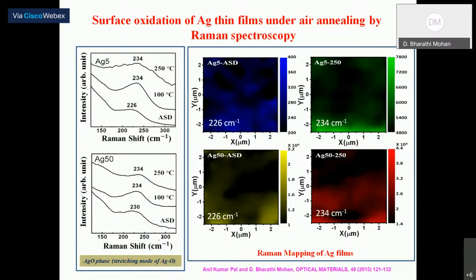One of the major problems with silver is the oxidation. So we need to study the surface oxidation of the thin film. So we have used Raman spectroscopy in order to understand the chemical structure of the silver thin film. And we found that there is a peak at 234, which corresponds to the stretching mode of silver oxide, confirming the formation of silver oxide. And the formation of silver oxide becomes much greater when you increase the film thickness and when the films are annealed at higher temperature, like 250 degrees Celsius.